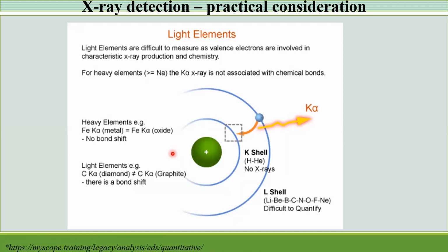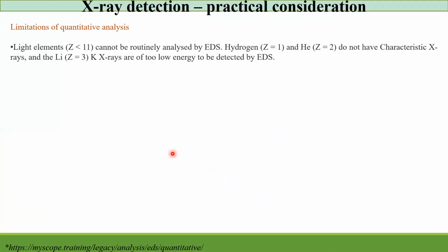As we know from the chemistry perspective, within the oxidation layer, whether it is from the iron rich region, the aluminum rich region, or the alloys, we know where the oxygen sits. So we just try to get only cations instead of the anion oxygen, and we calculate later what the possible oxide combinations in that region are.